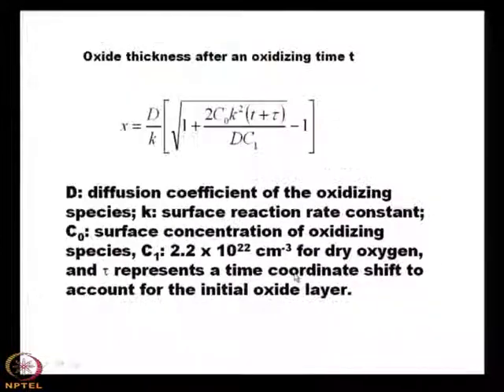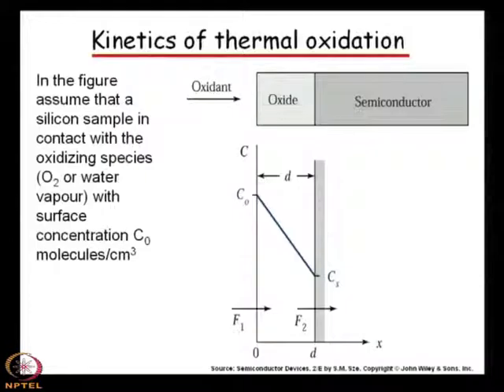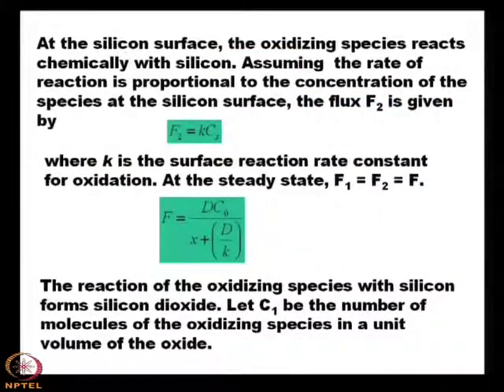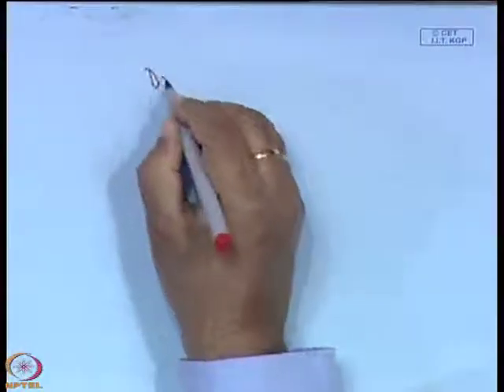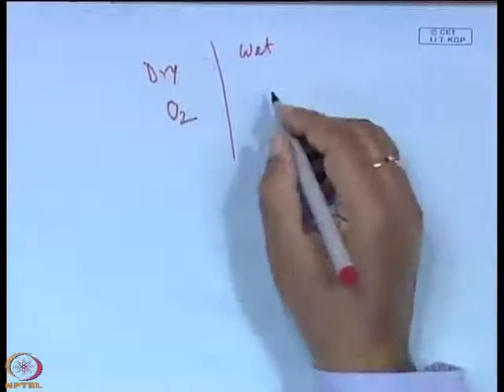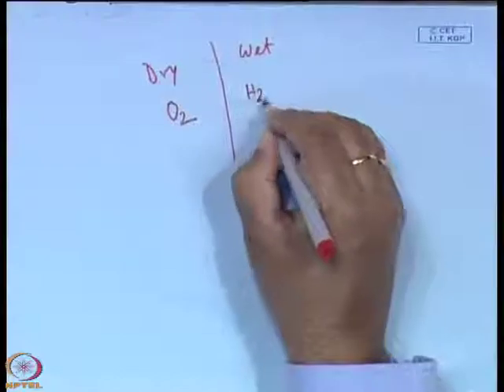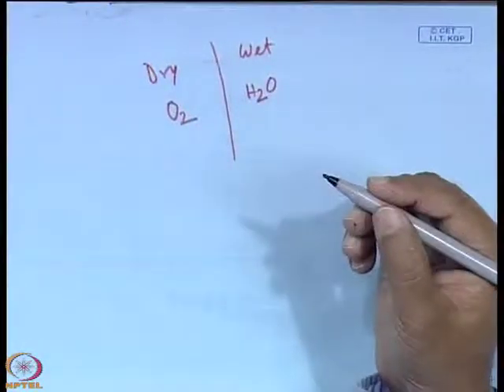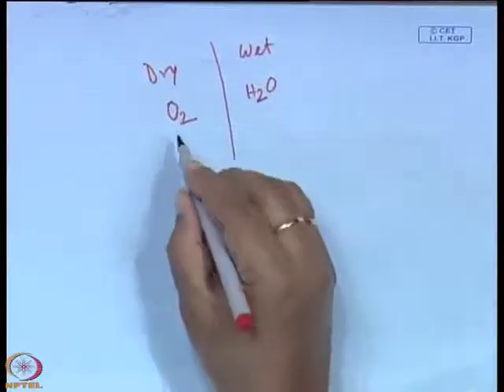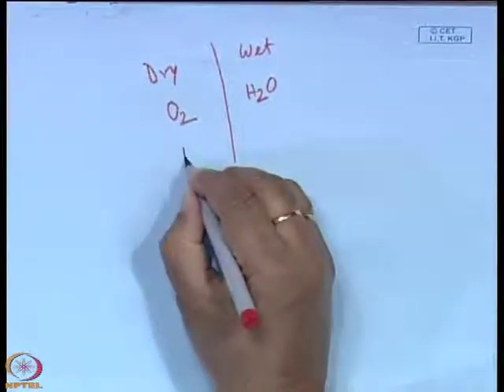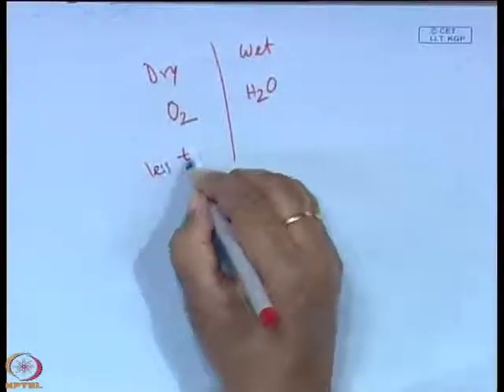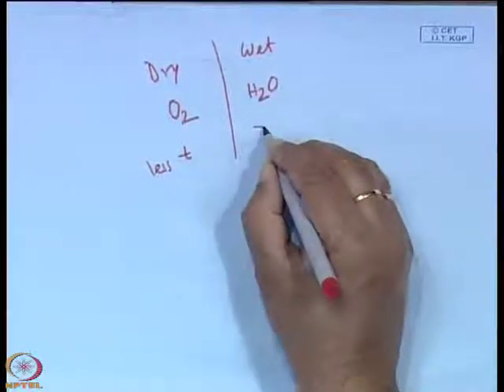So, now we can summarize our lecture. The oxidation can be of two types: one is dry oxidation, another is wet oxidation. For dry oxidation, we have seen that oxygen gas is used, whereas for wet oxidation H2O vapor, that means water vapor or steam, is used. We have seen that for dry oxidation the thickness is less, the value of T is less. For wet oxidation, it is greater than T for dry under the same condition.